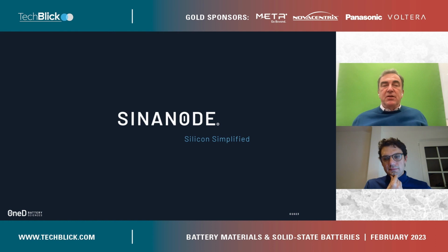Yeah. So in Palo Alto, the machine that we have has a single tube. That machine has a nominal capacity of about 25 tons per year. And we have operated that machine since 2018, so we perfected the process. But we are limited by the amount of silane we can get in Palo Alto with the permits. What happened in Moses Lake, the machine that I show in these slides, is basically 4 tubes, higher flow of silane, and then faster heating and cooling.